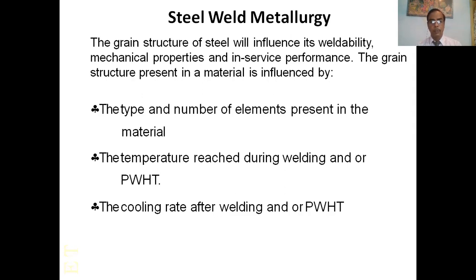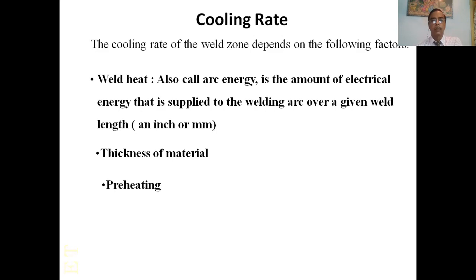Post-weld heat treatment. Both are post-weld heat treatment. Cooling rate of the weld zone depends on the following factors. Weld heat, also called arc energy, is the amount of electrical energy that is supplied to the welding arc over a given weld length, an inch or millimeter. Thickness of material and preheating.